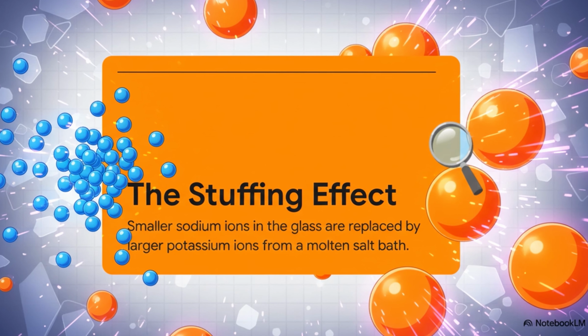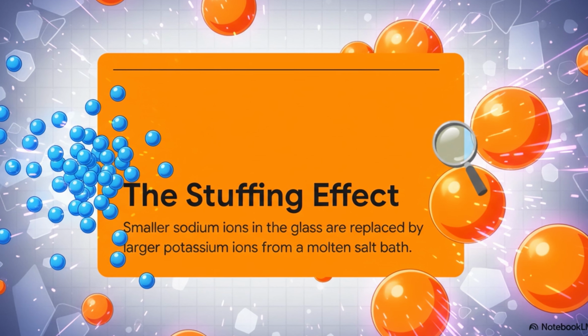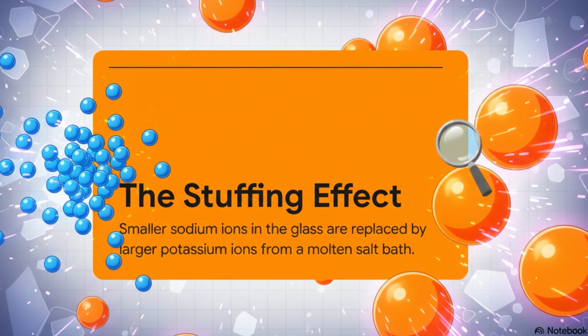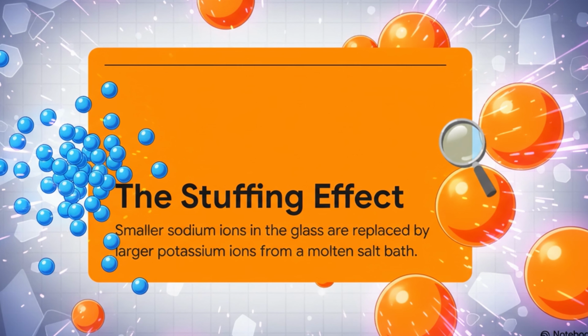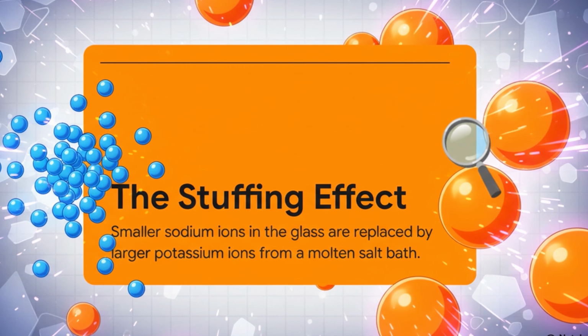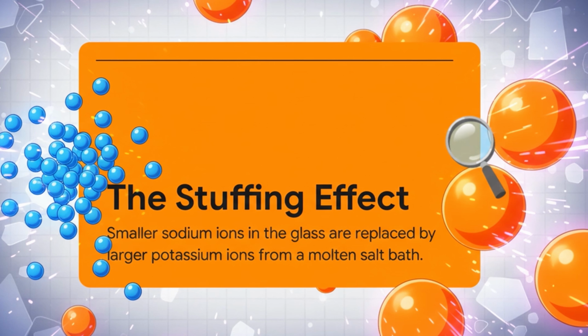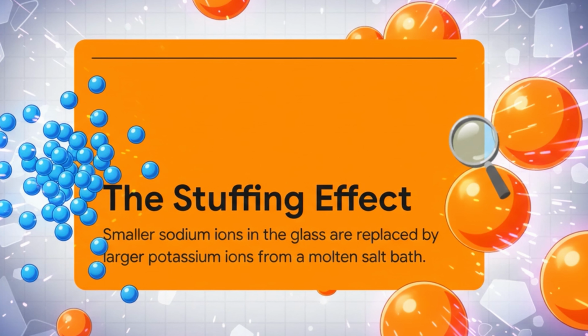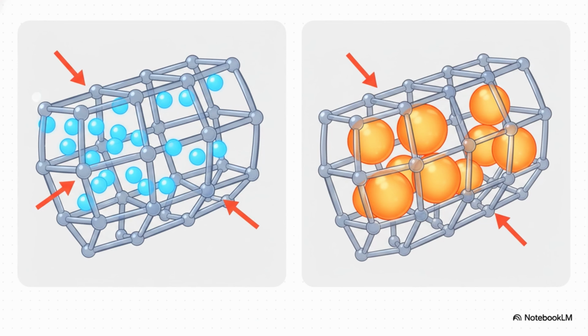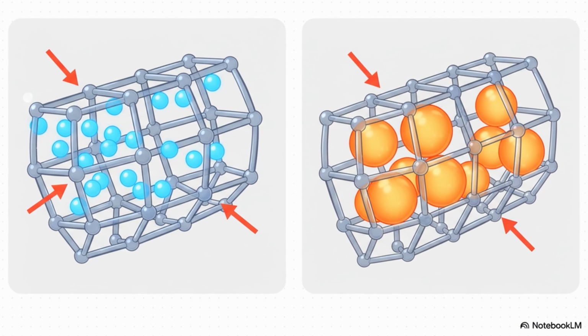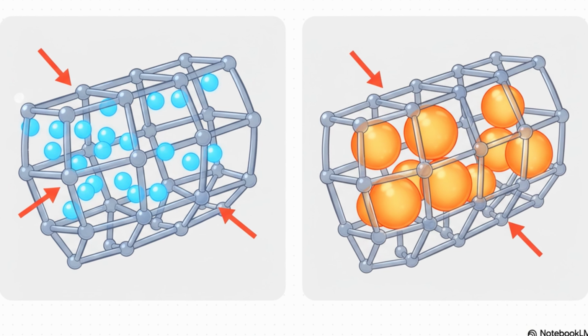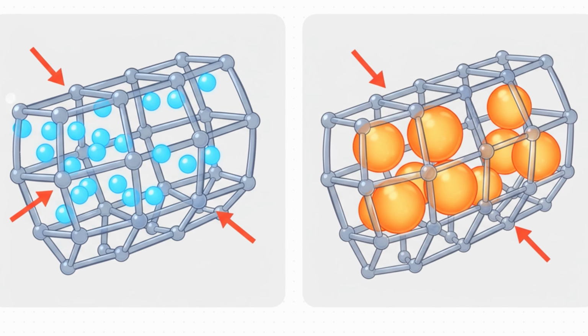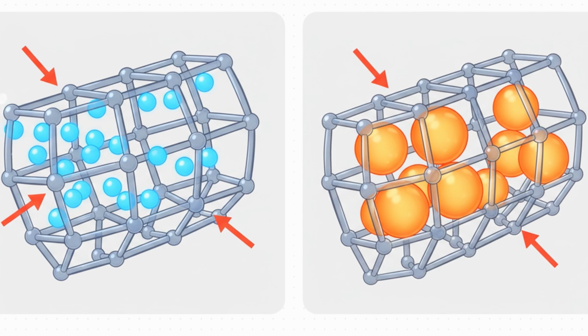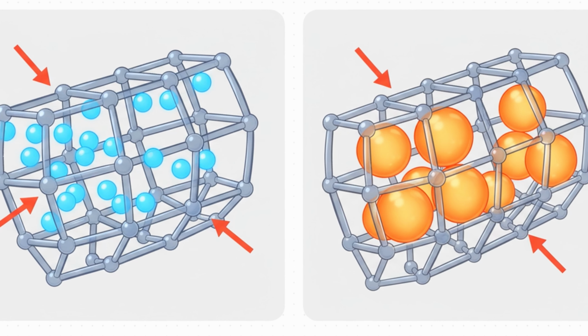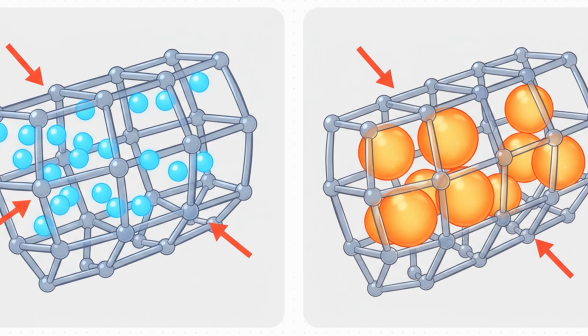Think of it like this. Smaller atoms are encouraged to leave the glass, and at the same time, the process forces much larger atoms from that salt bath to squeeze into the tiny spaces they've left behind. It's basically atomic level overcrowding, and it's completely intentional. To be specific, there are two key players in this atomic swap meet. You've got the smaller sodium ions, which are already hanging out in the glass, and they move out. At the exact same time, larger potassium ions from the molten salt bath get pushed in to take their place.